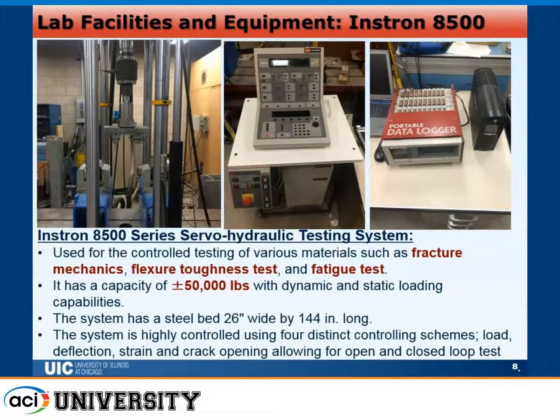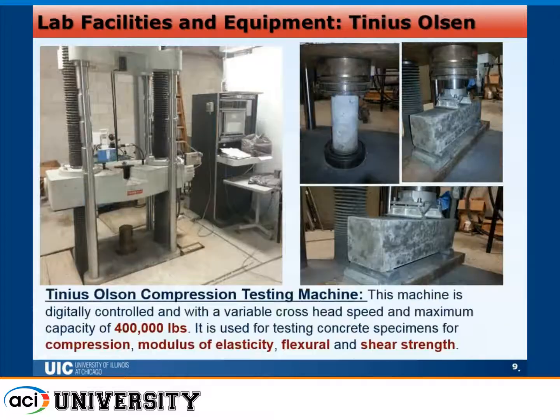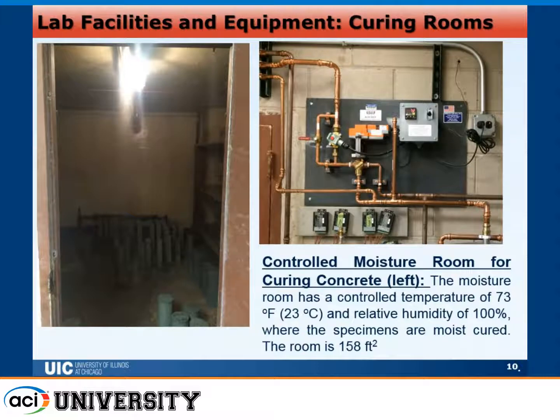And the testing machines that we used: a simple Instron machine, which is a servo loop, closed loop machine with a 50,000 pounds capacity load cell, and the data was collected on a separate data logger. For the strength results, we used a normal Tinius-Olsen machine with 400,000 pounds capacity to measure the compressive strength and the flexural strength.